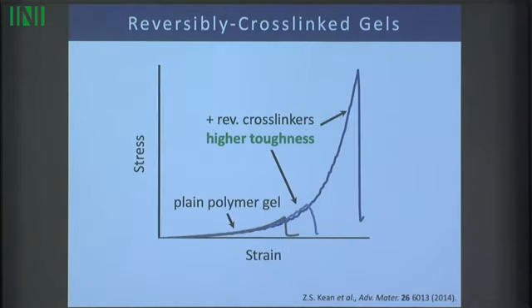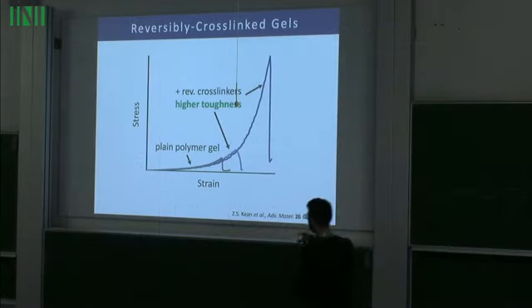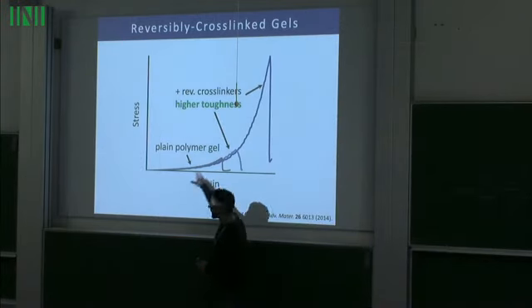What's observed in experiment is a very interesting behavior: if I design my reversible cross-linking complexes appropriately, I end up with this kind of stress-strain behavior. For those of you who are not mechanics people, this is just a plot of the restoring force I feel on the polymer gel as a function of how far I pull it apart, the strain. Okay? And the gray curve, which is a bit hard to see down here, is the plain polymer gel.